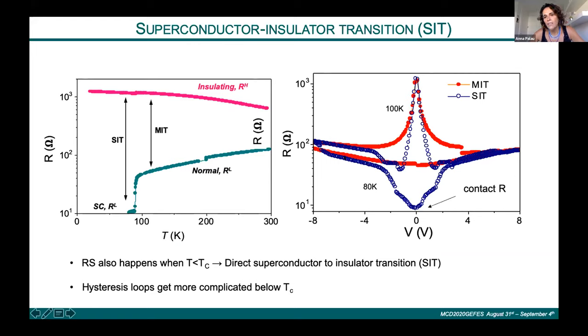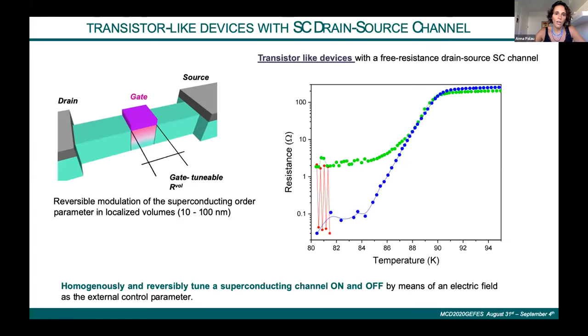The red points are the points obtained at 100K, and the blue points are the ones obtained at lower temperatures, below TC. We observe that we can drift the system from this low resistance state, the superconducting state, to this state, the insulating state. And this contact resistance that we measure in this experiment is because we are measuring in a two-point configuration, through the gate.